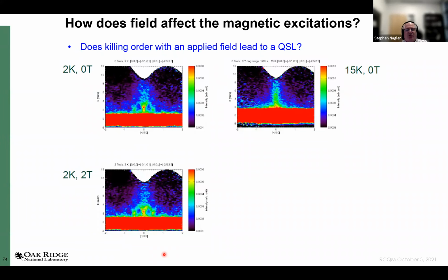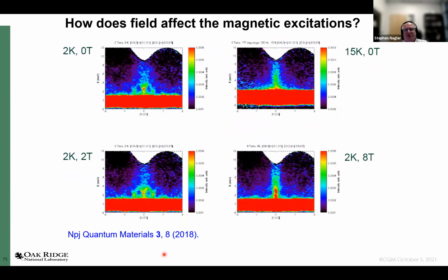But as soon as I go beyond the critical field where it disorders, the spin waves die and this continuum is present very strongly. So it looks a little different from this, but it seems that in this disordered state, whatever this disordered state is, we see only the continuum scattering.